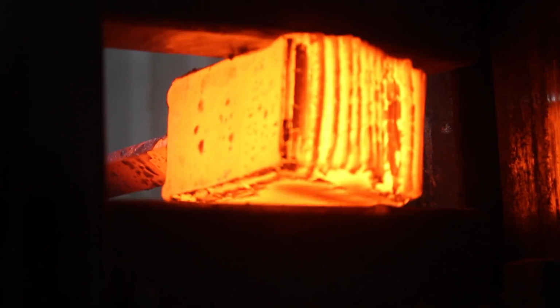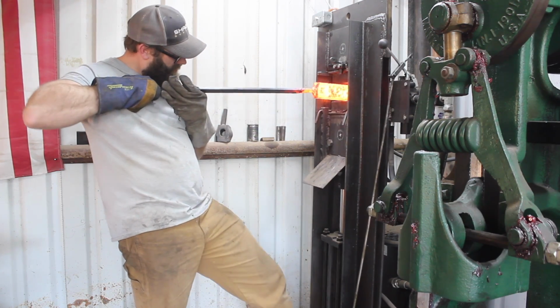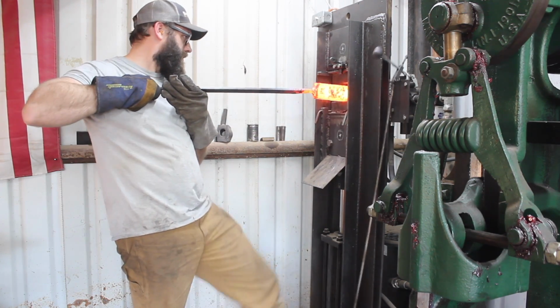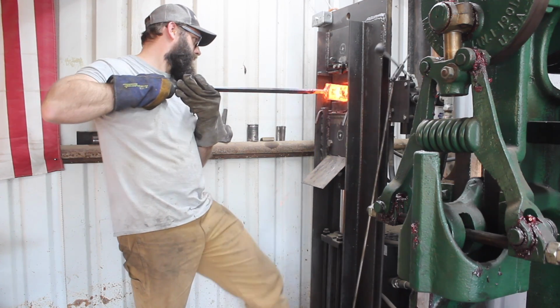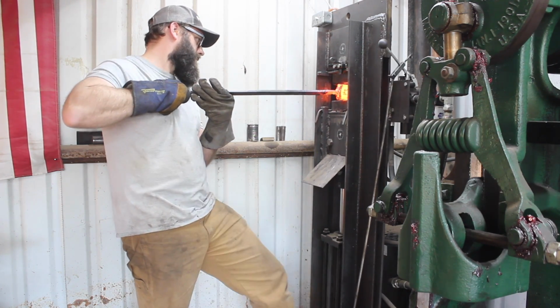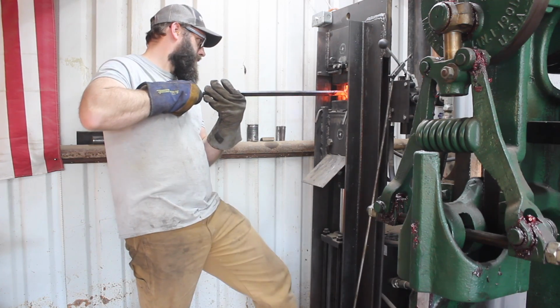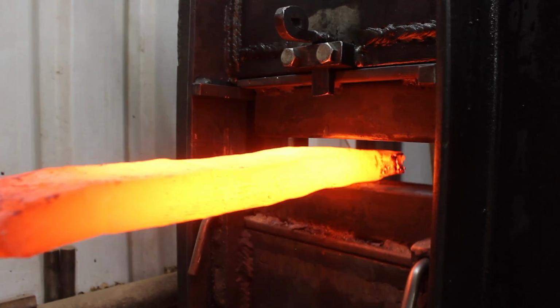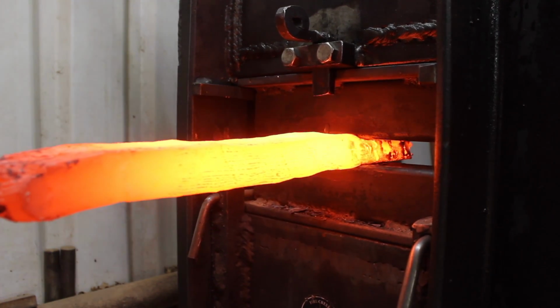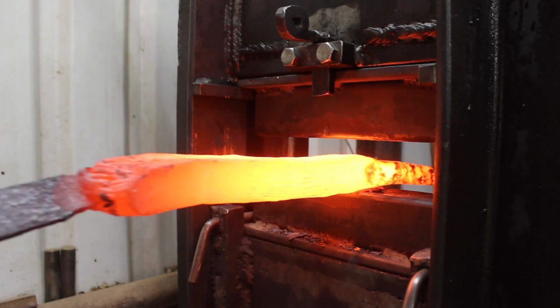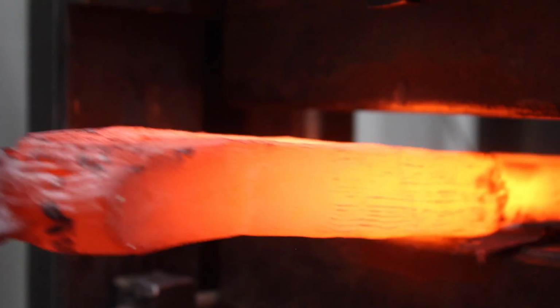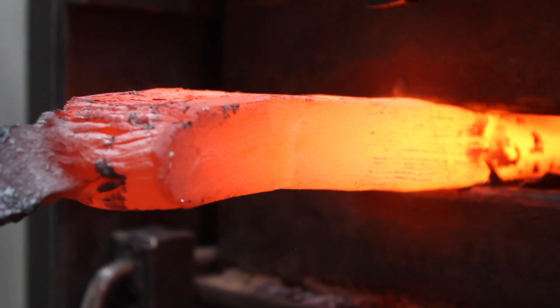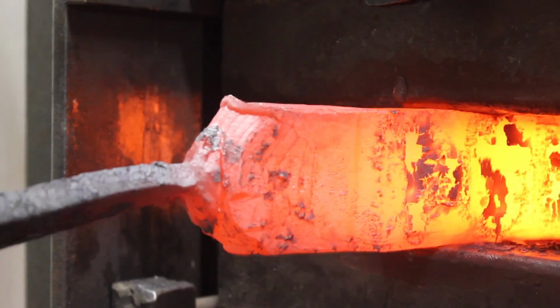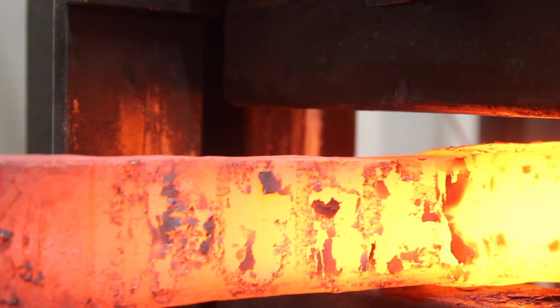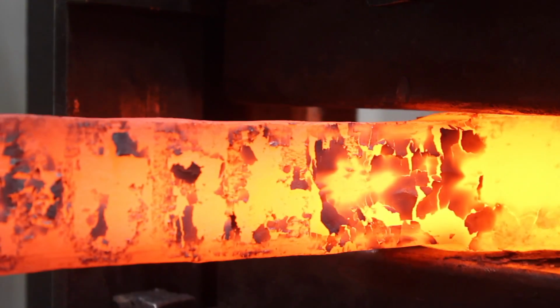You can see the iron oxide or forge scale break apart as that billet changes shape. This is where the forging press really shines. It works well for large cross sections of steel that can hold the heat for a longer period of time. And we'll work this billet down to about 1 inch thick, and the thinner you get, the less effective the forging press becomes. But it is definitely a very useful tool for forging these large billets.